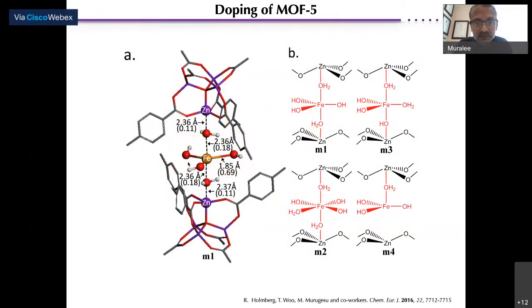So what's the environment around the iron? This is something where we sought help from my colleague Tom Woo to find out what these atoms around the iron centers are. Through computational methodology, they were able to find out that these three oxygen atoms belong to a hydroxide group, which is still kind of surprising to me because terminal hydroxides are not so common. We would have expected these to be water molecules and these to be hydroxide. But the lowest in energy they were able to obtain through this modeling is this structure.